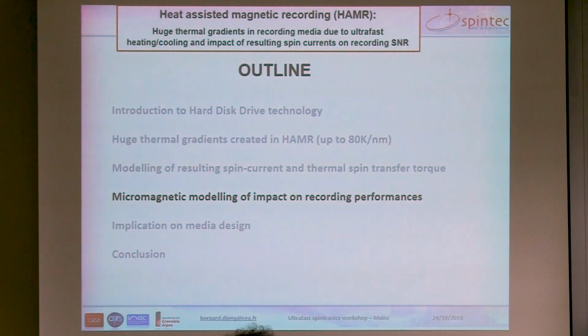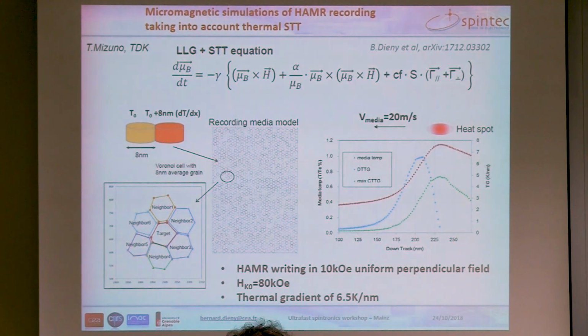So now I am going to show the impact on the recording performance, which can be deduced from micromagnetic modeling. The micromagnetic modeling was performed by Dr. Mizuno at TDK Headway. You see here a picture of the media, described by an assembly of Voronoi cells. The thermal profile was this one, calculated from COMSOL. And we assumed an anisotropy field of 8 Tesla at low temperature for this iron platinum type of media,